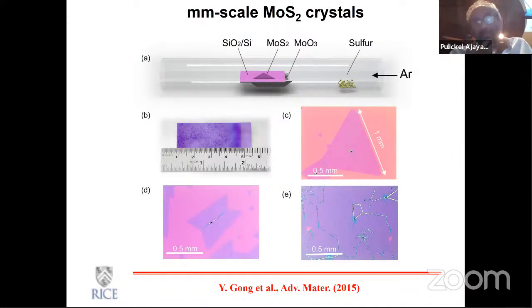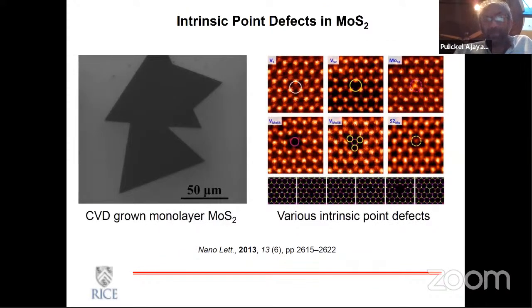One of the interesting things that we have pursued in our lab is to see how large crystals you can grow. And as you can see, by optimizing conditions, you can indeed grow millimeter-sized grains, millimeter-sized crystals of these without any grain boundaries. Doesn't exclude other kinds of defects like point defects, but certainly you can grow single crystals of these over large area. And again, most of this has been trial and error and finding the right conditions.